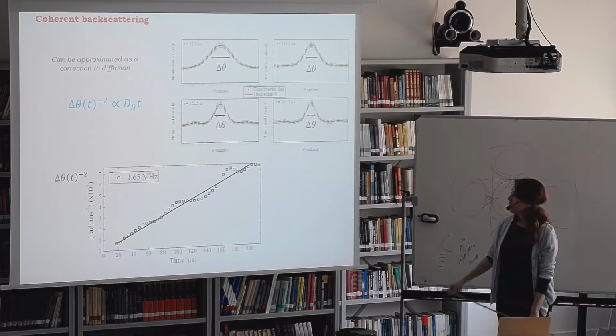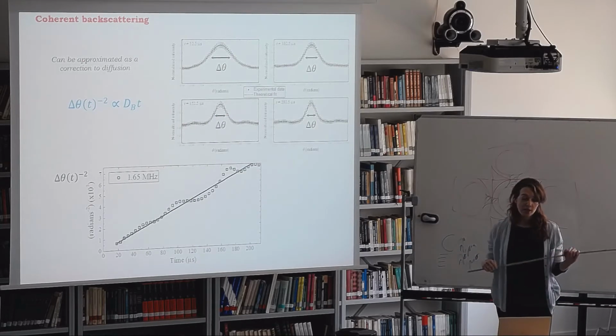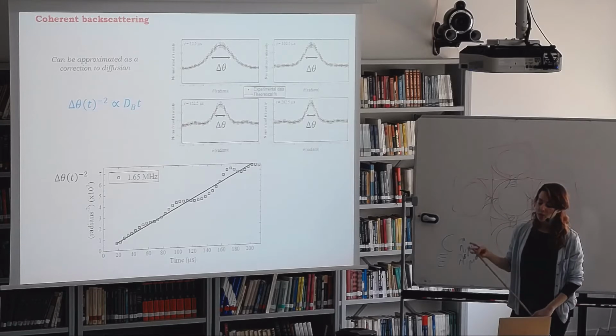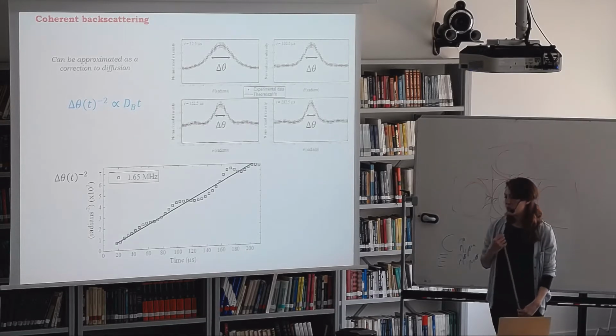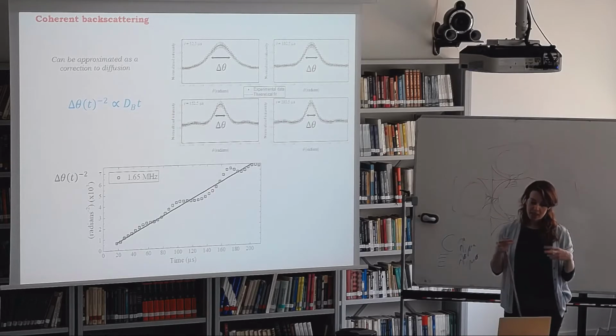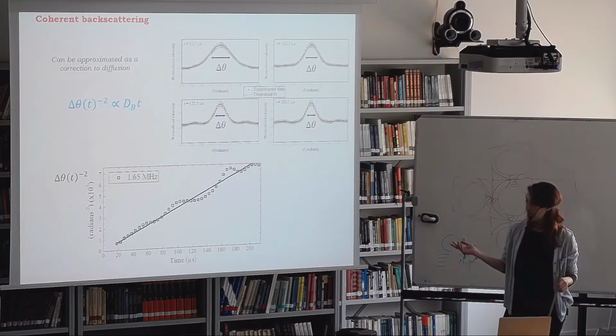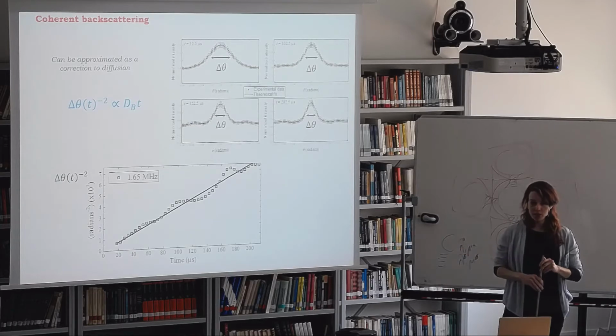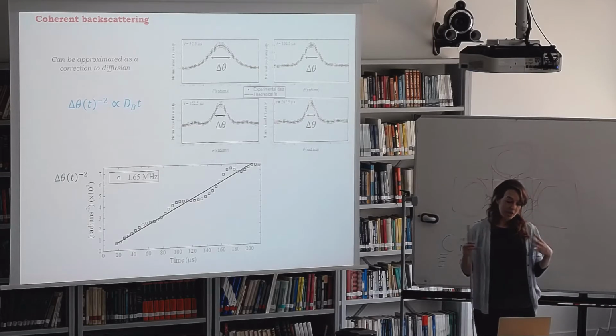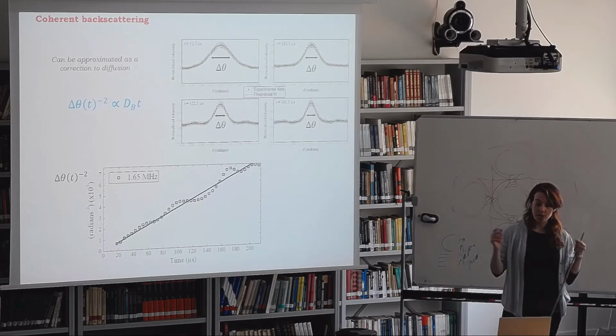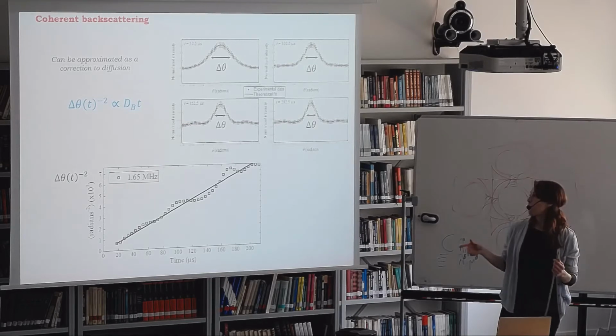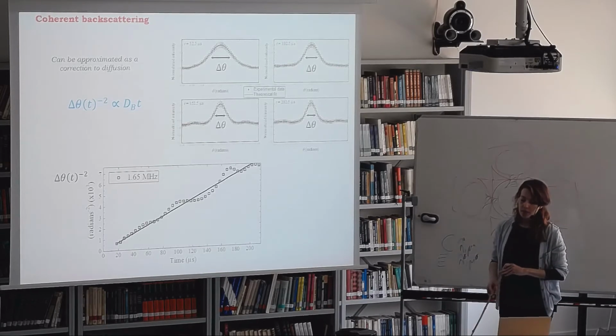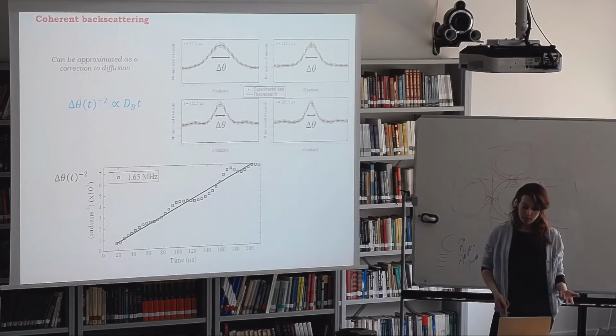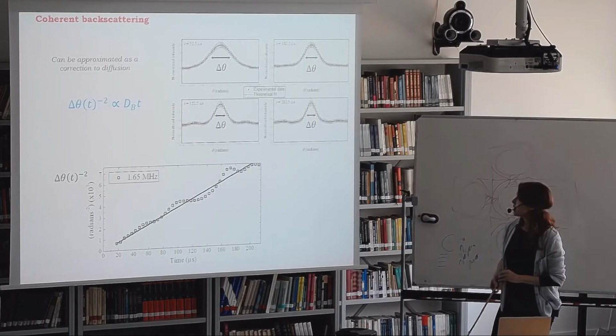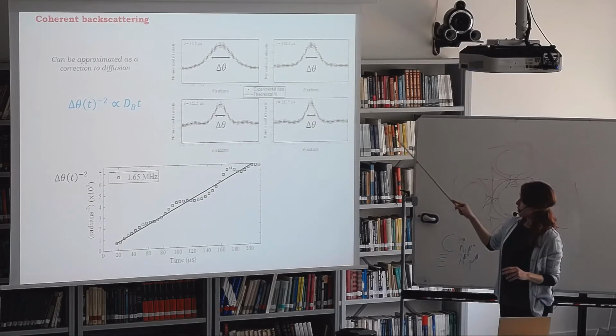Okay, so although coherent backscattering is not included in the diffusion approximation, it can be approximated as a sort of correction to diffusion. Because essentially, we've just not accounted for these reciprocal paths. I'm not going to show the calculation for the theory, but it essentially just involves manually summing up the contributions between all possible pairs of reciprocal paths. So when we do this, it gives us a correction to the diffusion equation. And this lets us fit our experimental measurements quite nicely.